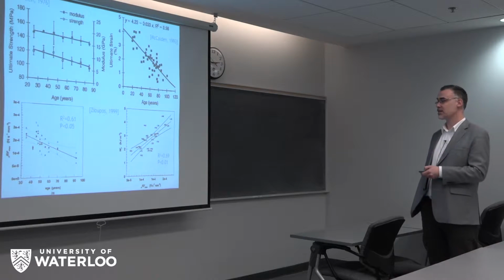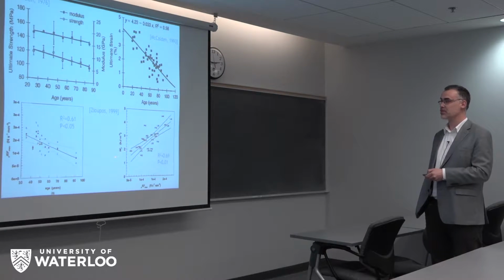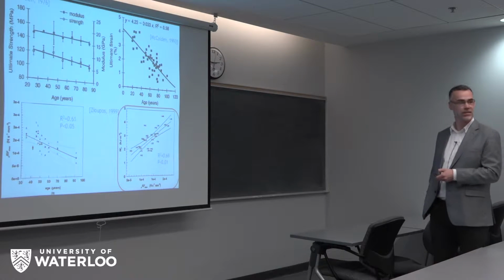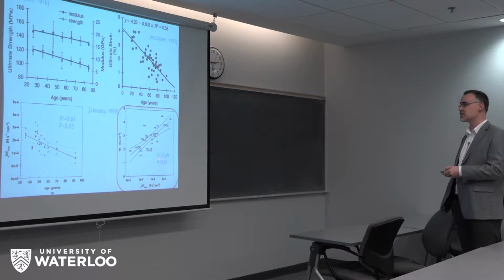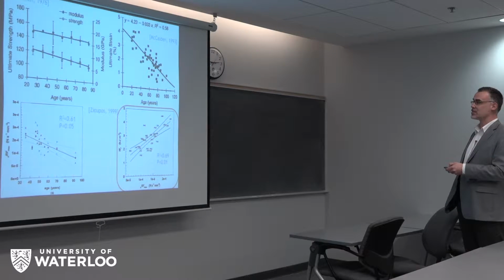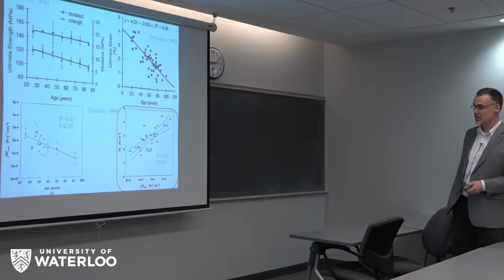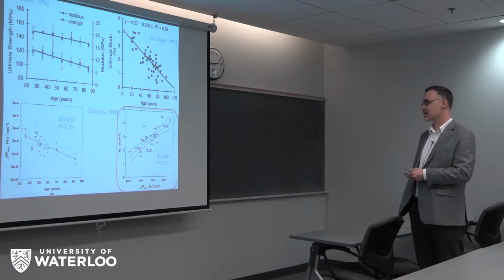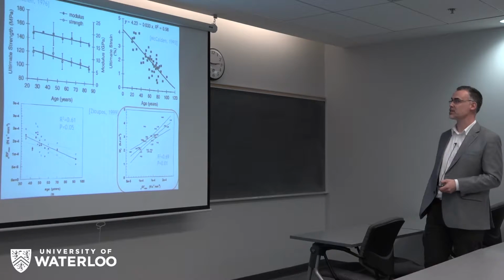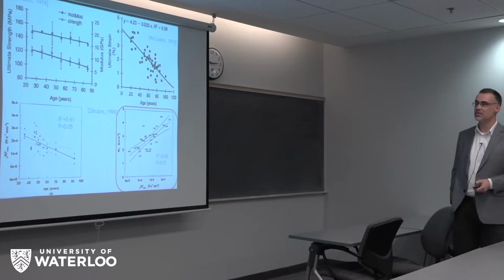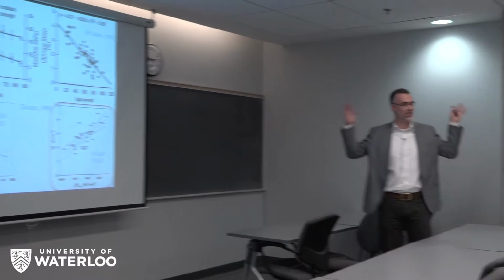And more importantly, for this talk, what he showed was there's a positive correlation between connectivity and work to fracture. And I want you to remember that idea because it's pretty important to the rest of this talk. And so what you ended up seeing was younger donors up here and older donors down here. So, but a strong, and an even stronger correlation with fracture toughness. So that was a key idea. So we weren't just sort of hypothesizing out of nowhere.